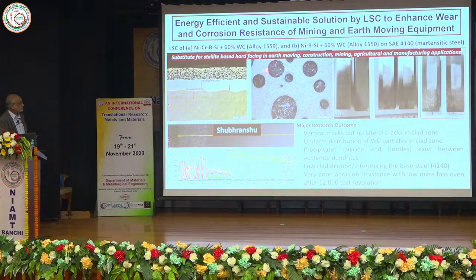This sphericity also tells us that there is very little dissolution during the process itself, so particles remain solid and can be dispersed. The advantage is that if you try to disperse tungsten carbide in normal metallic systems, there will be a lot of gravity segregation. With these thin clads, you can actually maintain very good uniform distribution.